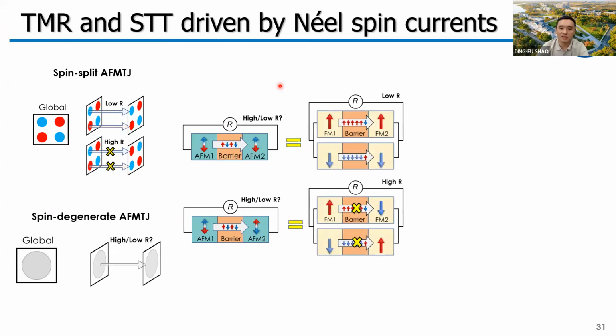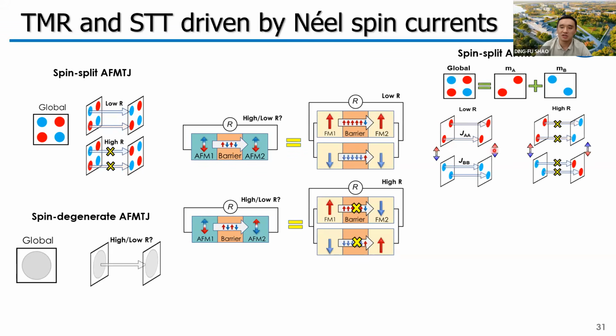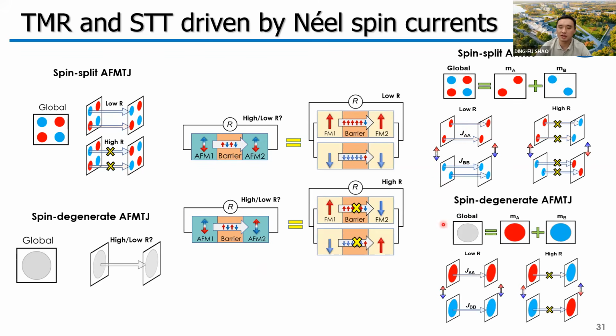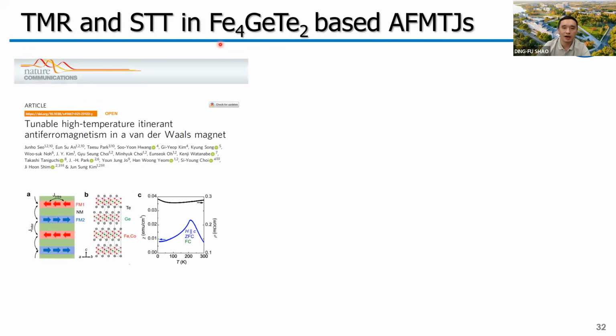But the demonstration of the Néel spin currents may make us recognize that we are in fact matching the sublattice resolved conduction channels with the help of the Néel spin currents. In this case, we can also use antiferromagnets with spin degenerate Fermi surface if they support the Néel spin current, because the sublattice resolved Fermi surface or conduction channels in these antiferromagnetic metals can also be well spin polarized. So with the help of the Néel spin currents, we can match the sublattice resolved conduction channels and get sizable TMR. In order to demonstrate this, we check the 2D antiferromagnetic metal Fe4GeTe2.